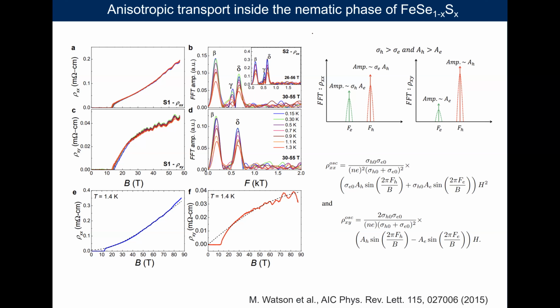How we try to explain this is that if the system has very mobile Hall carriers, like we saw before in thin flakes as well, then that signal will dominate the rho xy component much more than the rho xx. So these are the ratio in amplitude caused by the Hall pocket or the electron pockets. And if one plugs into a multiband model, one can try to explain the differences in amplitude in quantum oscillations. So the rho xx and rho xy components seem to be affected in a different way.